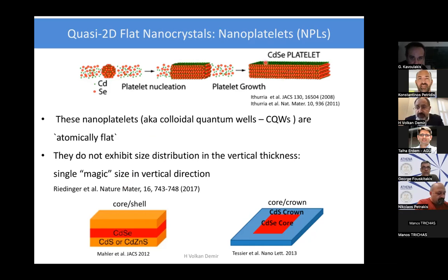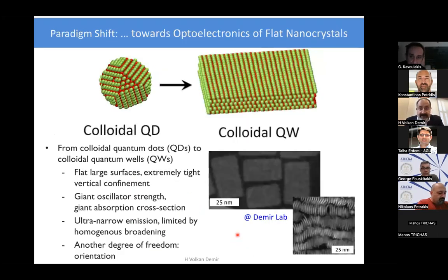Of course, one can do core, but as has been demonstrated, you can coat everywhere. So this is now isotropic growth, shell coating everywhere, particularly top and bottom, obviously the largest areas. But then you can choose to go for only anisotropic growth, which means one needs to extend only the lateral parts, therefore still keep the same starting vertical confinement. This was therefore for us a paradigm shift towards this optoelectronics of flat nanocrystals.